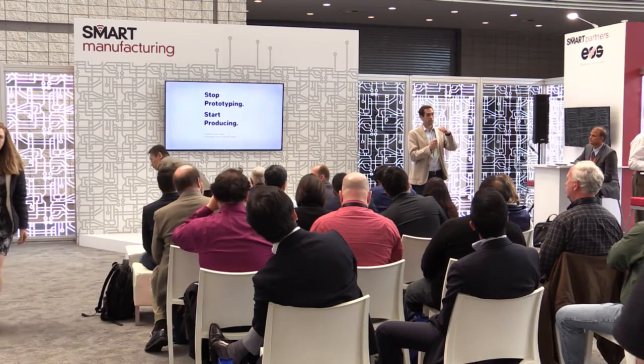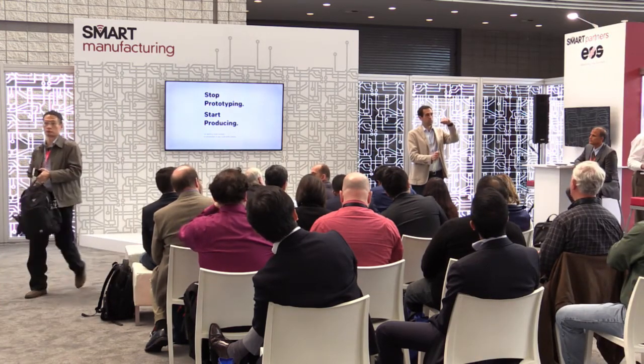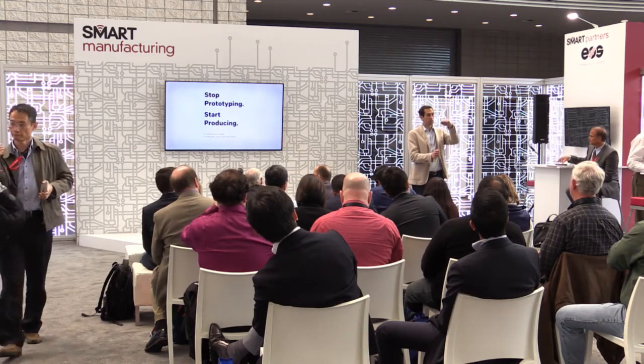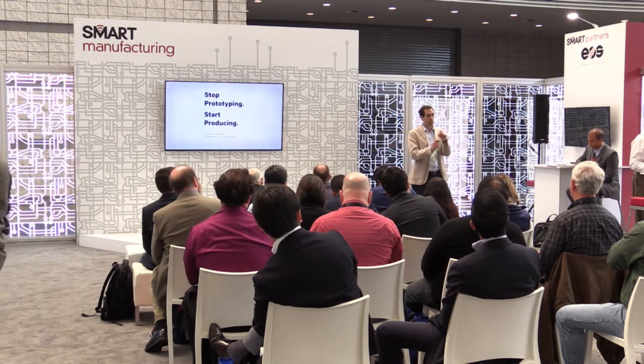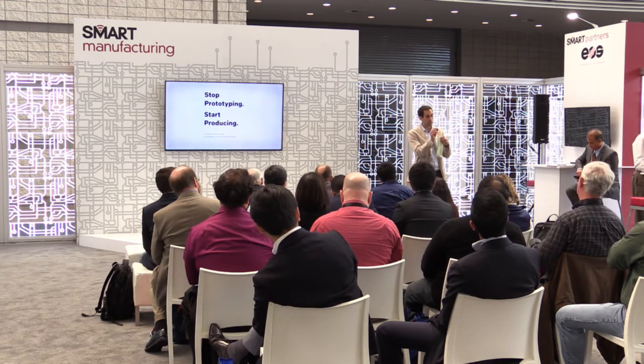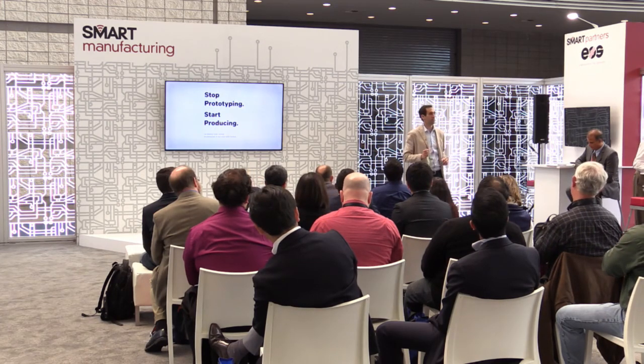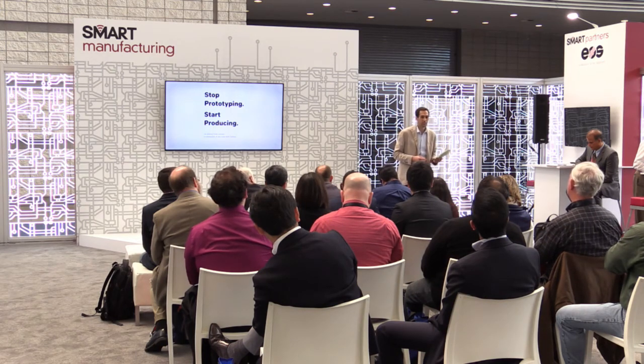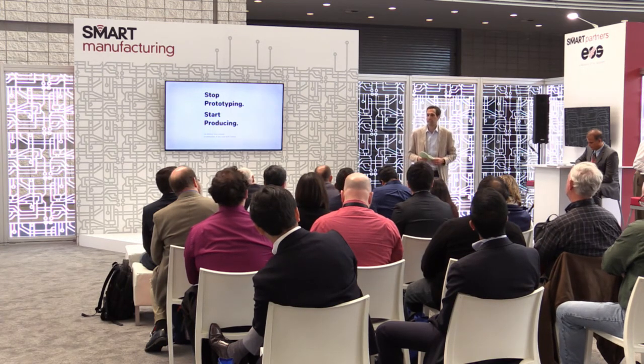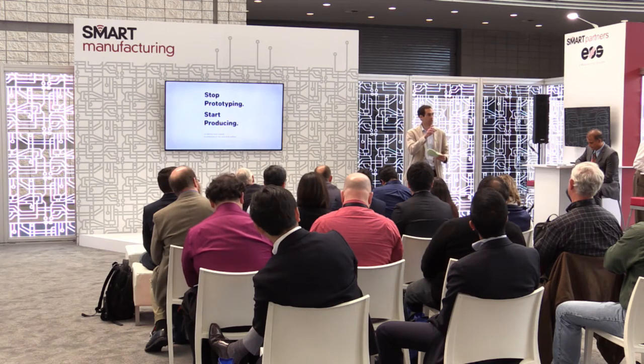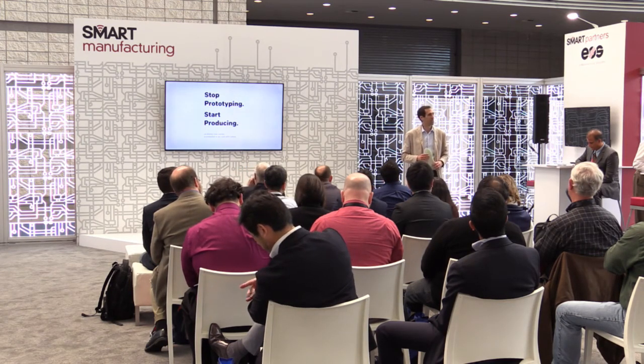So when you test and try to pull it apart, you get a cohesive failure, not an adhesive failure. So it doesn't fail at the point where you've done the intersection. Instead, it fails at the weak point of the material. So we're seeing great things. It's kind of like an overmolding process, and we're seeing really great applications, especially for doing things like taking an elastomeric material and surrounding a rigid polyurethane material to create a handle or a grip. That's something where we're seeing a lot of interest right now. So that's been fun to see.